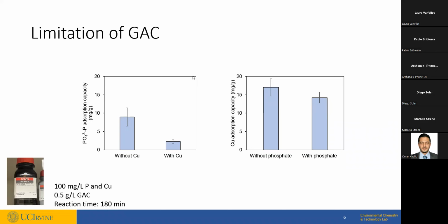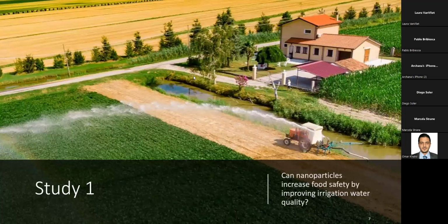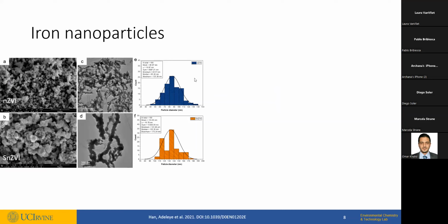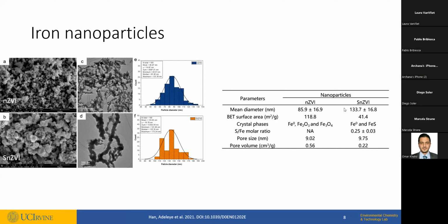So that's where we decided to see if nanoparticles can potentially work better in this type of system. The nanoparticles we used are called nanoscale zero valent iron. So it's just Fe in the zero valent state, as particulates, and the size is in the nanoscale. And sulfidated NZVI, which is essentially when the NZVI was being prepared, we added a source of sulfide so that there is some FeS species. This table summarizes the properties of the two nanoparticles.